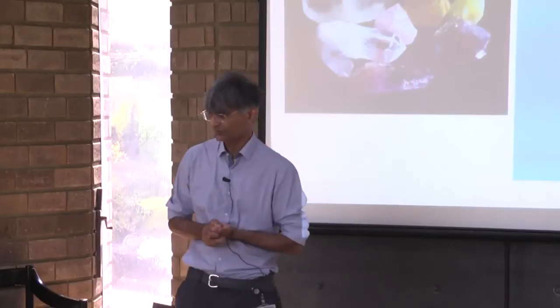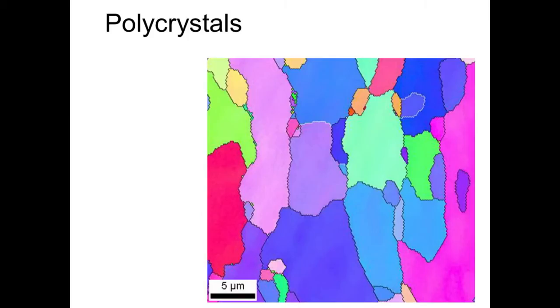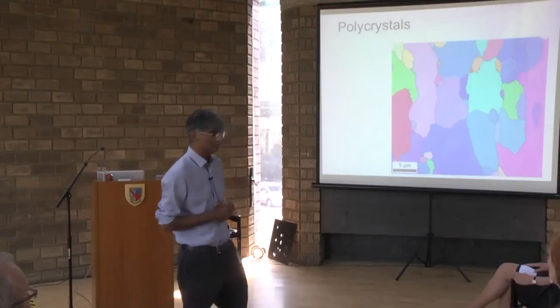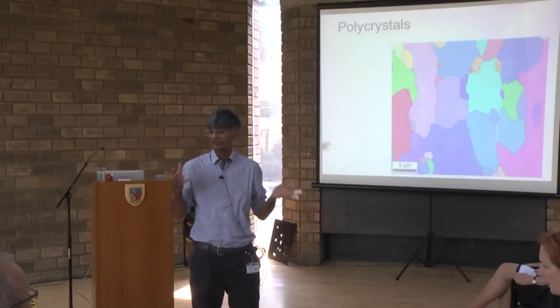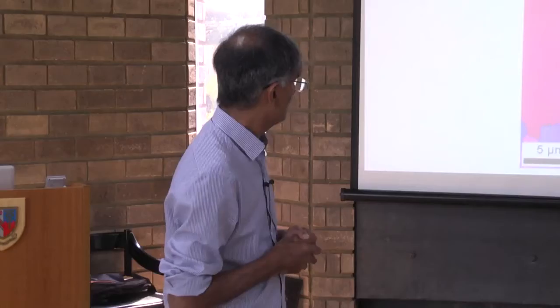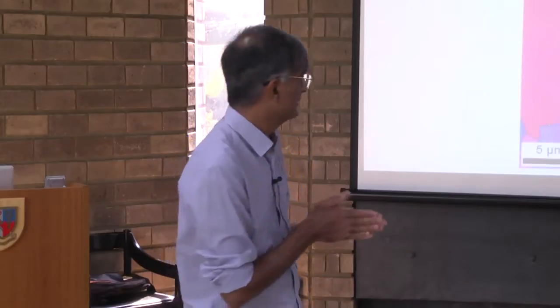But the vast majority of metallic materials are not single crystals. They are what we call polycrystals. That means we pack crystals together, and the dark lines that you see between the crystals are boundaries, grain boundaries. And the closer spaced those boundaries are, the stronger your material becomes. So if you want to make strong materials, you've got to pack a very large density of interfaces per unit volume of material. That means make the crystals as fine as possible.